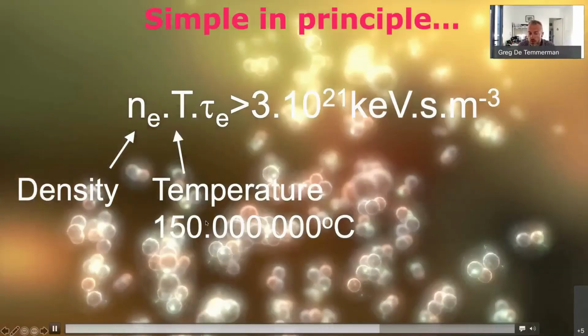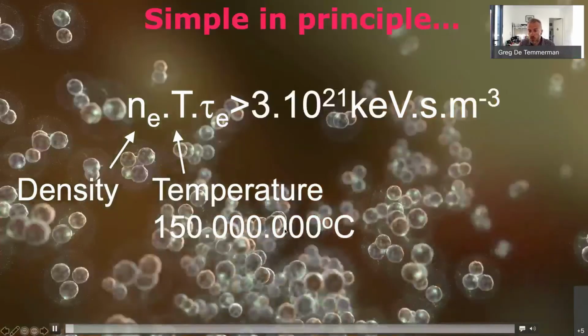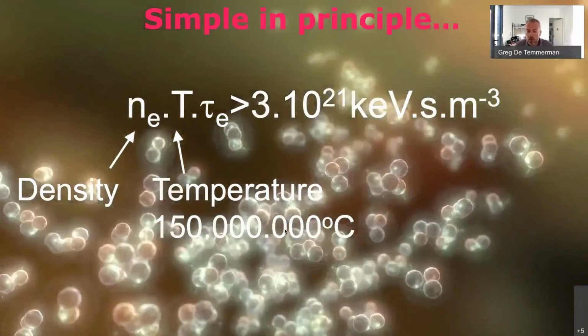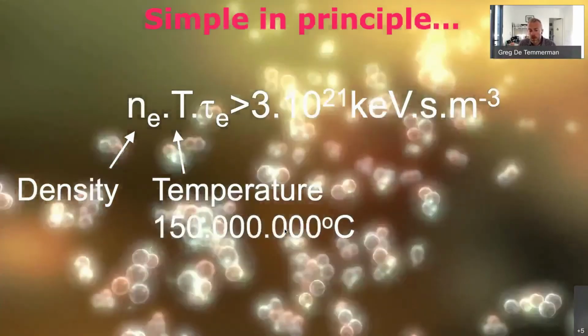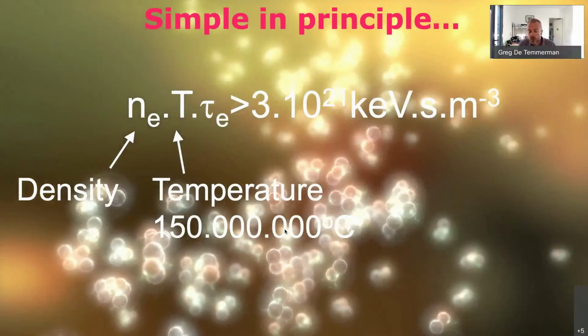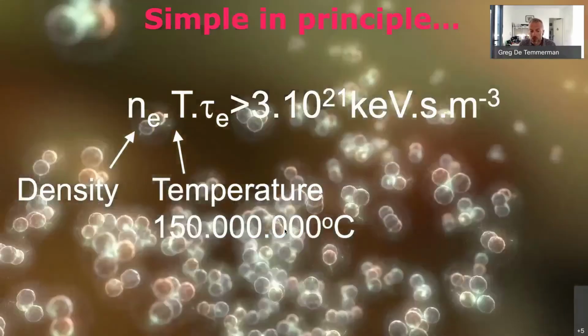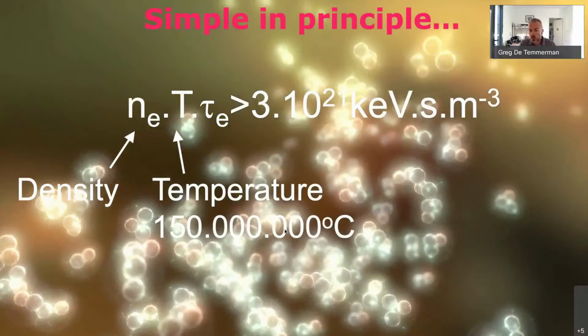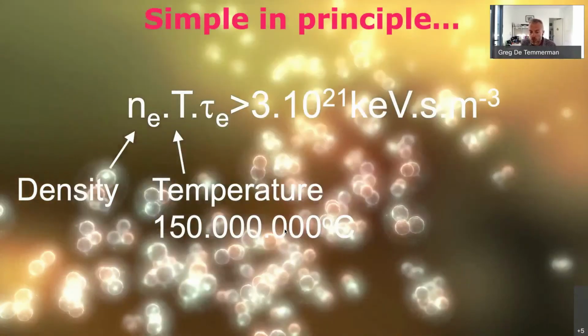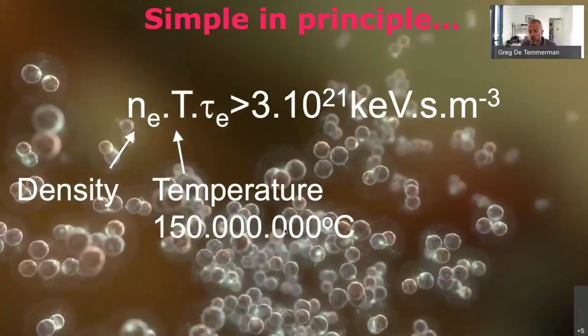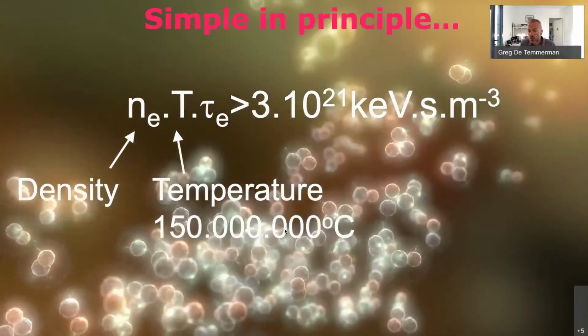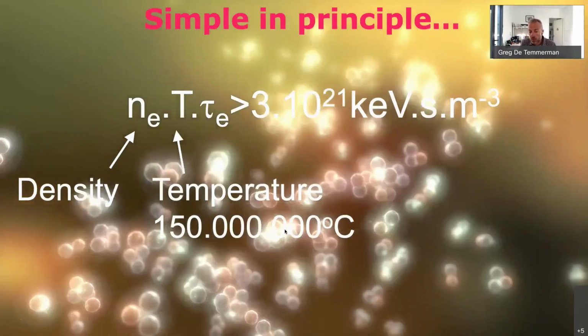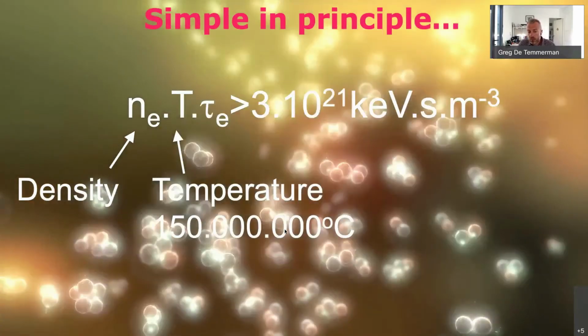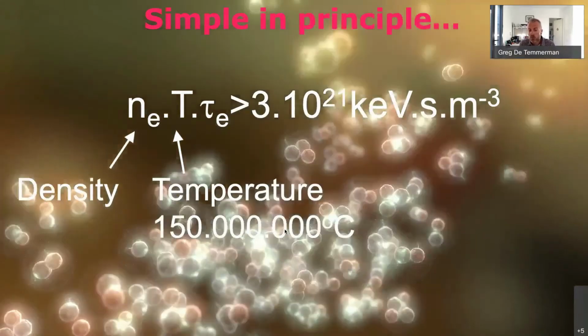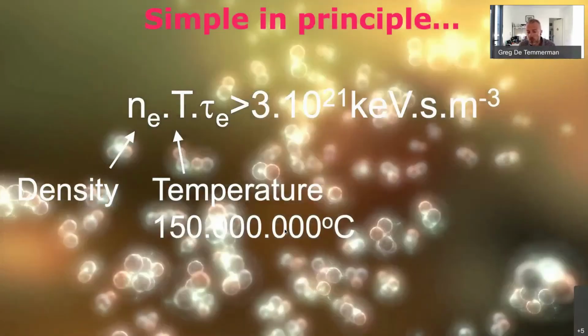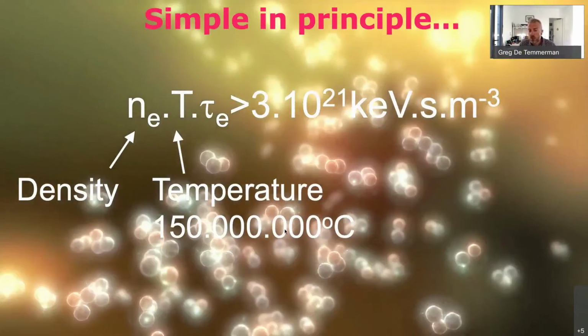Why do we have to go to those kinds of temperatures? It is because when you try to fuse particles, if you remember a bit about chemistry or particle physics, you basically have a charged nucleus. So the nucleus is positively charged with an electron spinning around. If you remove the electrons, you still have two positively charged particles, which you are trying to put very close together because you want them to fuse. So you have to have the particles getting close enough together for the strong interaction force to act and then to fuse the particles. And that can only happen if you are able to go above the repulsion force that you have between the positively charged particles. And the way to do that is to have collisions at very high energy.